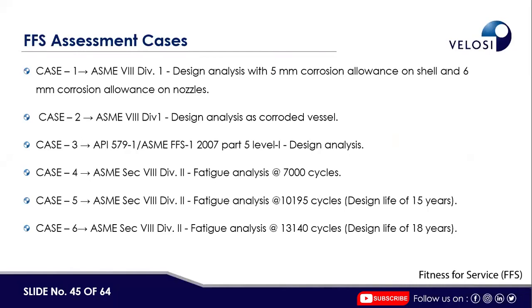First one without defects. Case 3, basically API 579-1, Part 5, Level 1 design analysis. Then Case 4, fatigue analysis with 7,000 cycles. Case 5, fatigue analysis with 10,195 cycles. And Case 6 with 13,140 cycles. We try to see up to which number of cycles can be acceptable for the cyclic service.